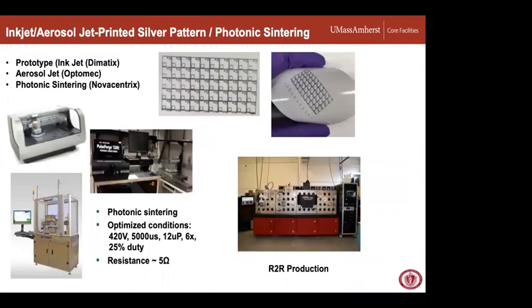So basically, some of the workhorse capabilities that we have in the roll-to-roll facility are the inkjet and aerosol jet patterning of printed ink. So silver's been the workhorse that most people use. We've had some of the students and research groups look at both carbons and copper, for example, which you can get in ink form. But regardless, both of these techniques are digital. So you put in a design, you load it on the computer, and then it'll print that out. Basically, you're working now with the substrate and the specific ink properties to optimize that pattern so it doesn't bleed out and be larger than you want, as well as it doesn't bubble up and form something that just won't adhere or stick to the substrate.